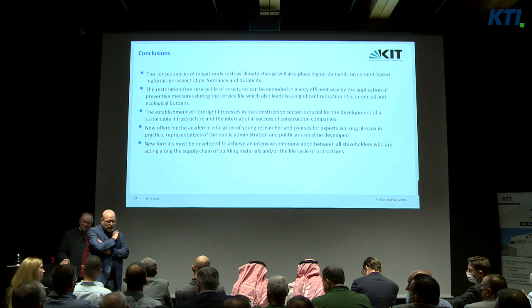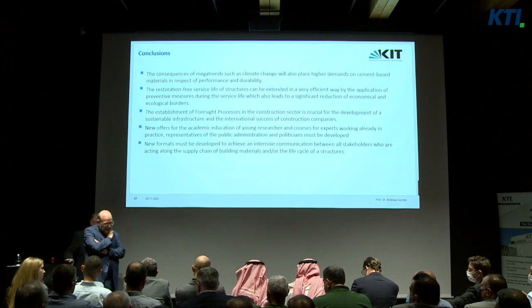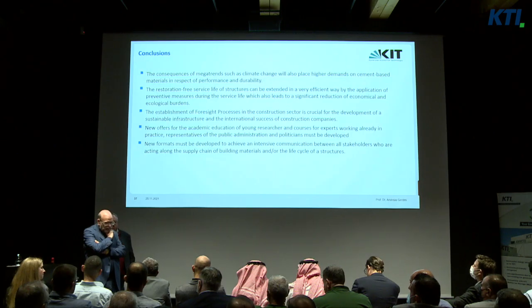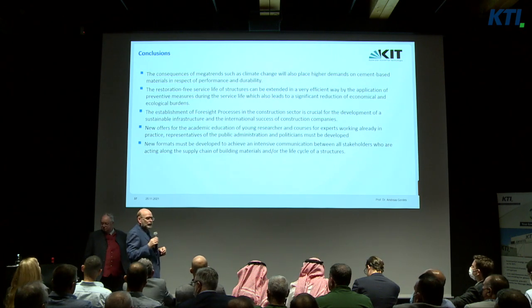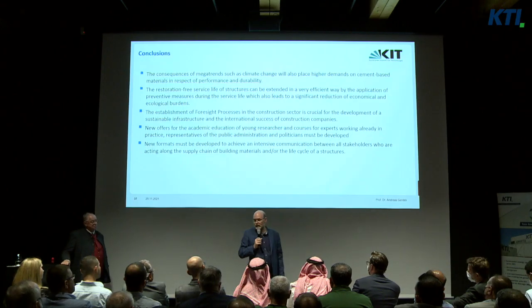Excuse me, you mentioned some chemical to be sprayed on the concrete. Definitely there is some repair required for the existing concrete before applying this spray. And what about the reinforcement inside? We call it a silane-based impregnation. It is a silicon organic compound which penetrates into the concrete, and if you use the right material, the penetration depth is around 5-6 millimeters. That means the covercrete protects your impregnation and therefore your surface protection system.